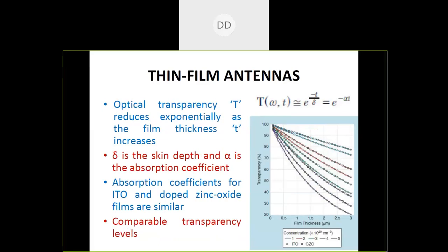The skin depth for optical wavelengths we can determine, and for this we need the mass of the electron, the permittivity values, and the optical frequencies. All these factors come into the picture while deciding the skin depth of the antenna. And the absorption coefficients for ITO and different doped zinc oxide films are similar, and thus we can use comparable transparency levels. So in place of ITO, we can use different doped zinc oxide films because their absorption coefficients are similar.